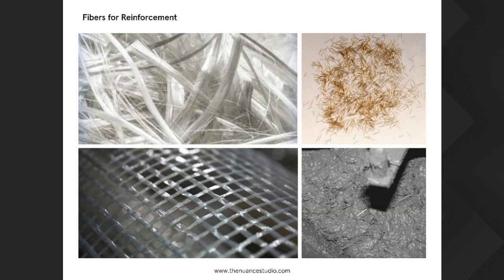Now, they're also fiber reinforced, as I told you. These are the kind of fibers that are used to reinforce the concrete. We don't use any kind of steel rebars, but these fibers are mixed with concrete when they are still liquid, and then they're cast. So these fibers are completely in the matrix of the concrete, and every square inch is also reinforced by itself. It's not just metal rods, where you have to bend them and keep them in the mold and cast. So that really doesn't happen. This allows us to cast products in whatever kind of shapes and forms we would look at.